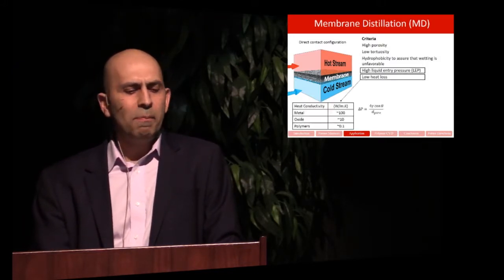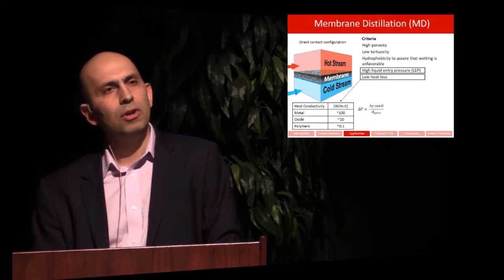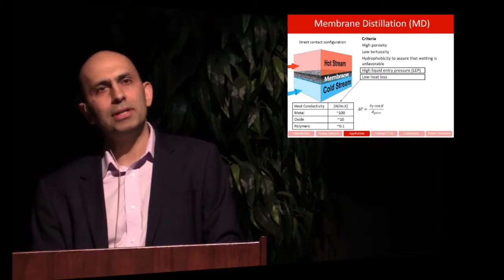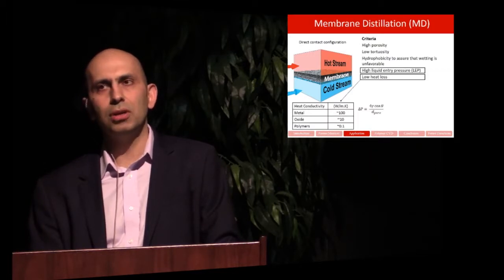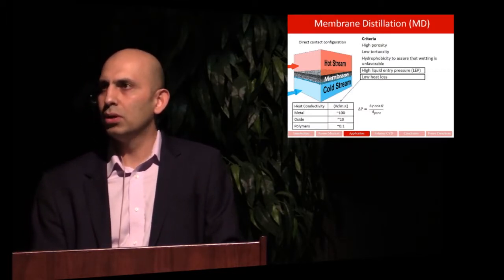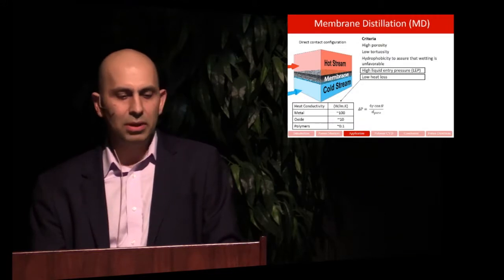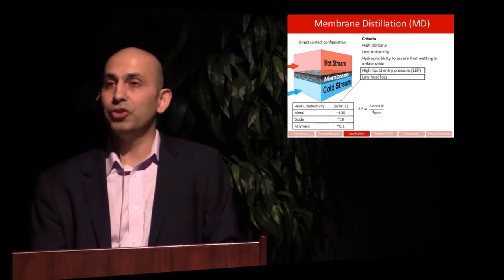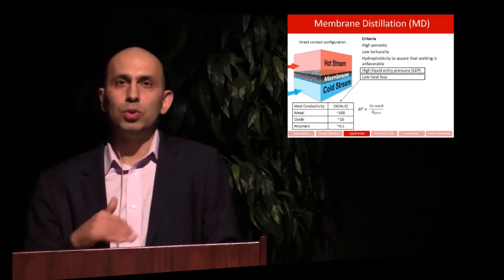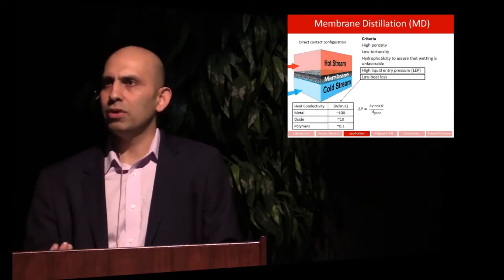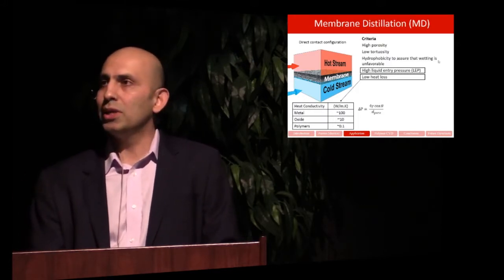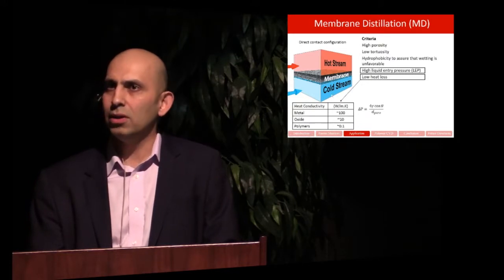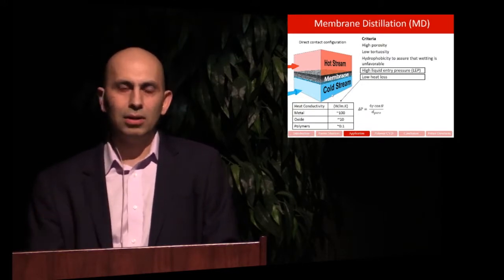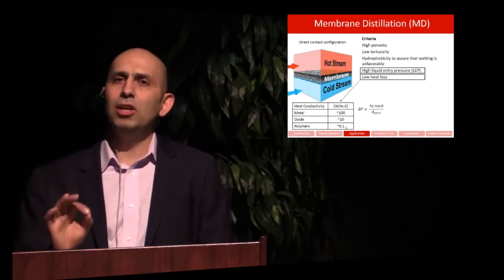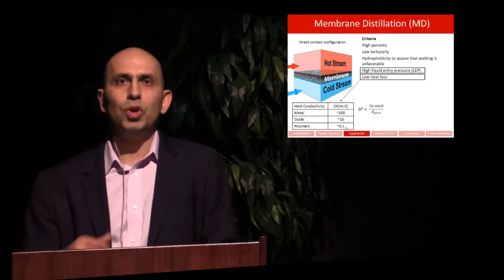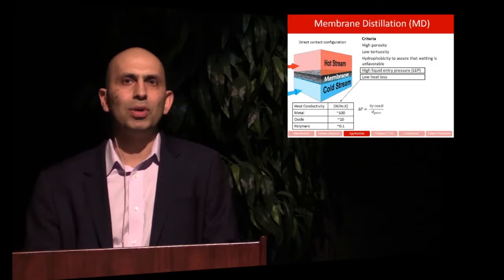So it turns out from all the materials of interest, if you look at the properties that are required for membrane distillation, polymeric materials are the choice. One of the reasons is simply because this process is thermally driven. So we do not like to lose the heat that is the driving force of the process. And one way to lose the heat is to conduct the heat through these materials or through that barrier. So if you have a material that has a very low heat conductance, you're going to have the best possible scenario in terms of choice of materials.